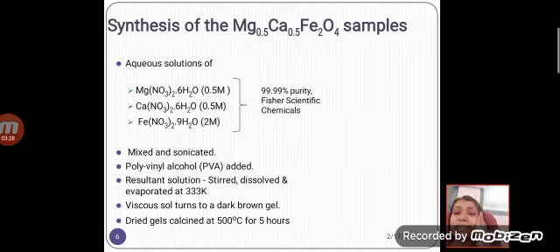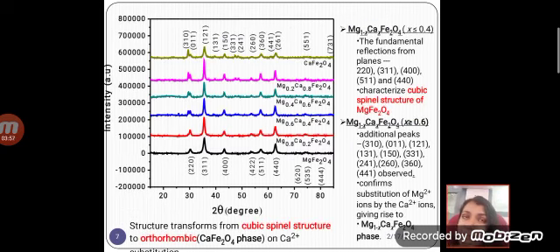So now let us see the synthesis of the magnesium calcium ferrite samples. We started using aqueous solutions of magnesium nitrate, calcium nitrate and ferric nitrate. These solutions were mixed and sonicated, and PVA, polyvinyl alcohol, was used as the gelating agent. The resultant solution was stirred, dissolved and evaporated at 333 Kelvin until the viscous solution turned into a dark brown gel. The dried gels were then calcined at 500 degrees Celsius for 5 hours. The resulting sample was powdered and ground finely to obtain fine powders.